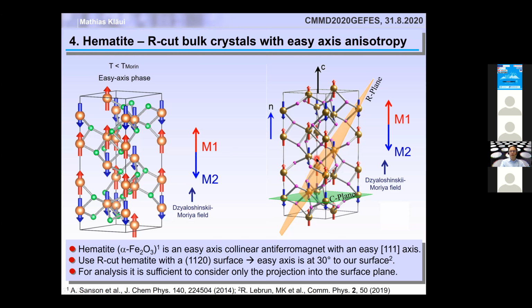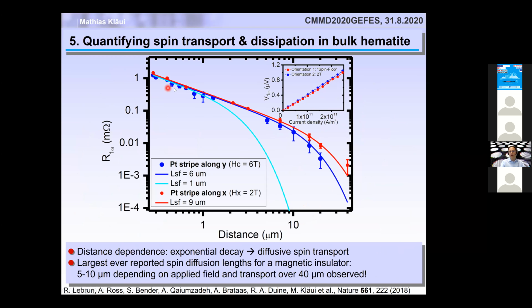And so then what we did is we measured the signal as a function of the distance between the injector and the detector. And the surprising finding was we get transport over 40 micrometers. So this was as long as the best ferromagnetic insulators like YIG, but in an anti-ferromagnet. And what we could also see is that there seems to be a dependence on the direction and on the field that we apply. So that is not something that just depends on the material's properties, but there are more things happening.